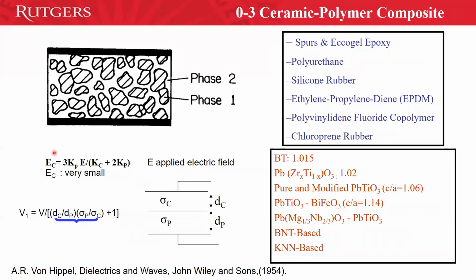Look at this applied electric field in the composites, and it comes from the relationship between the dielectric permittivity of the polymer and the dielectric permittivity of the ceramic. So if you apply about maybe 100 kV for polymer, you get only a few percent on the ceramic. This is from von Hippel; I derived this simple relation to show that the voltage applied to the ceramic depends on many variables. And then the best thing is to have a very thin polymer between the ceramic particles, as well as matching their electrical conductivity.